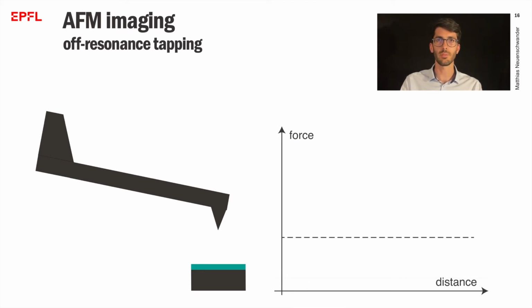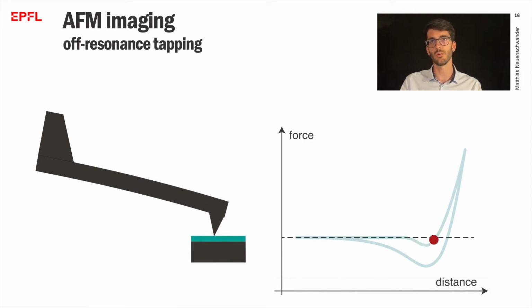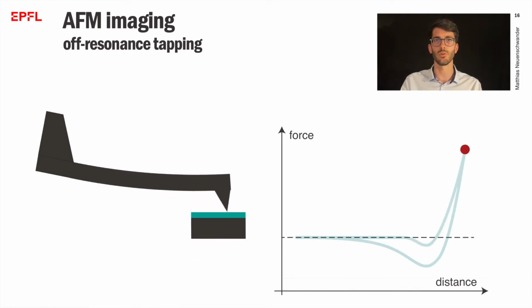In off-resonance tapping, the sample is moved up and down a few thousand times per second. When it gets close to the cantilever, the tip snaps onto the surface and is then pushed up until reaching a maximum force.